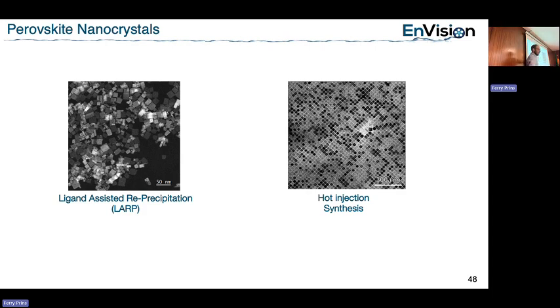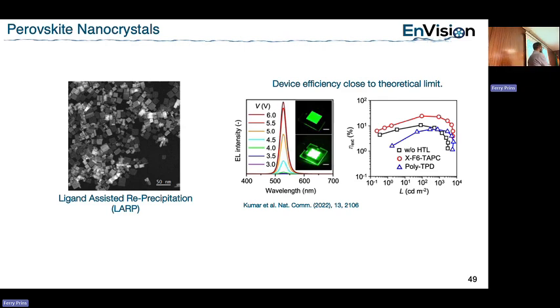The little movie I showed in the beginning - actually the morphology is quite disordered, there's a lot of size polydispersity. This is what they call the ligand-assisted reprecipitation method, and this is what you get. But still, you get this, and you make LEDs out of it, and people see that you can make LEDs close to the theoretical limit of how good they could be. So apparently it doesn't really matter - this is again the same story. Perovskites are this magical material where you really don't need to work very hard to get good results.